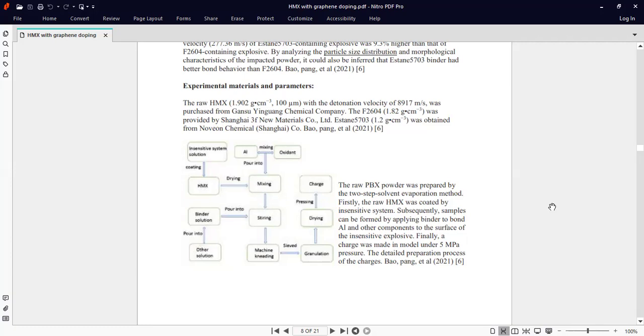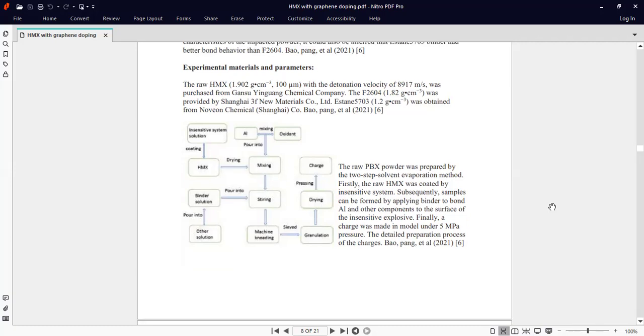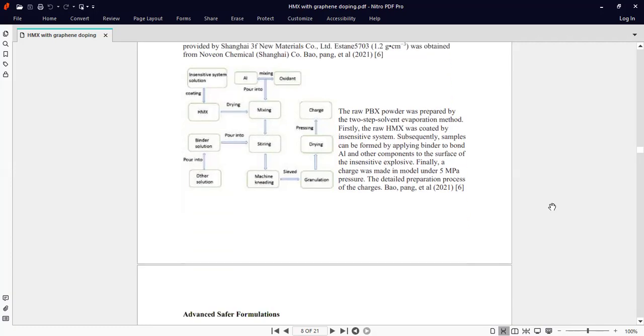The raw PBX, which is plastic bonded explosives powder, was prepared by the two-step solvent evaporation method. Firstly, the raw HMX was coated by the insensitive system. Subsequently, samples can be formed by applying binders to bond aluminum and other components to the surface of the insensitive explosive. Finally, a charge was made in a mold under 5 MPa pressure. The detailed preparation process of the charges.